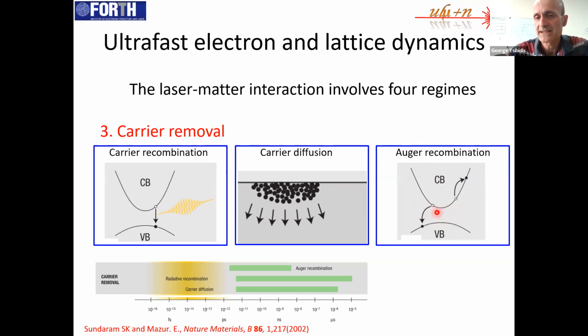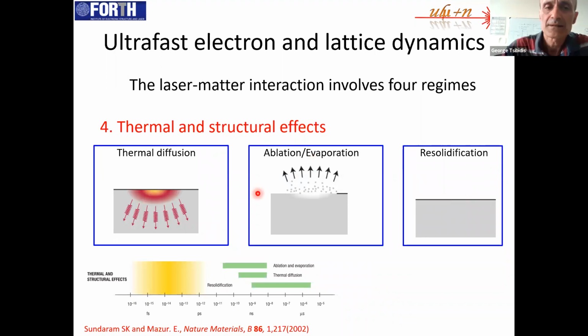which involves three particles. So the electron falls into the valence band, and then another electron, due to this excess of energy, moves into a higher state. And for thermal effects, we have the thermal diffusion. This happens when the electron system has already transferred its energy to the lattice system. Then the lattice system has been heated, and then we have thermal diffusion, heat diffusion inside bigger depths. And if the energy of the lattice system is very big, then we have mass removal.